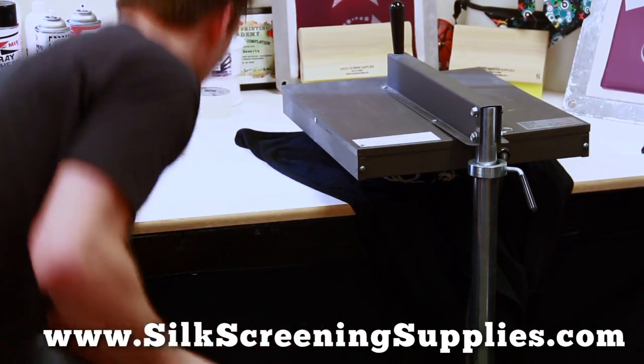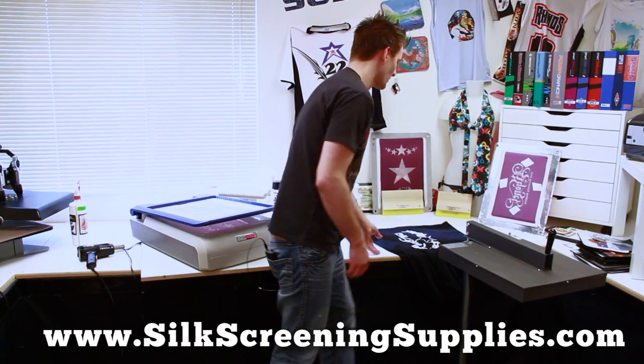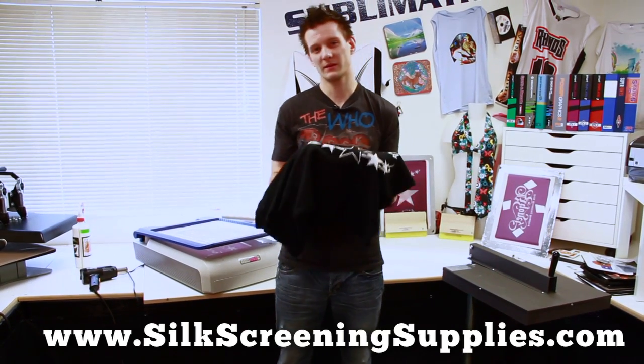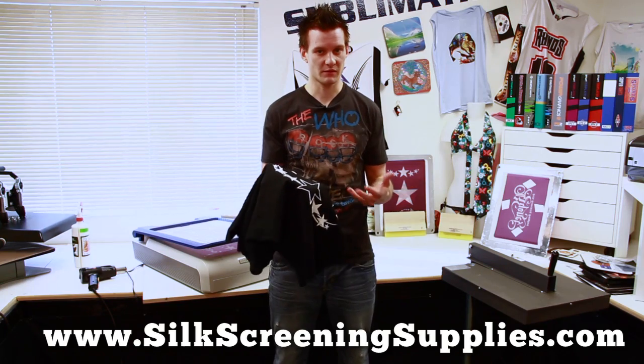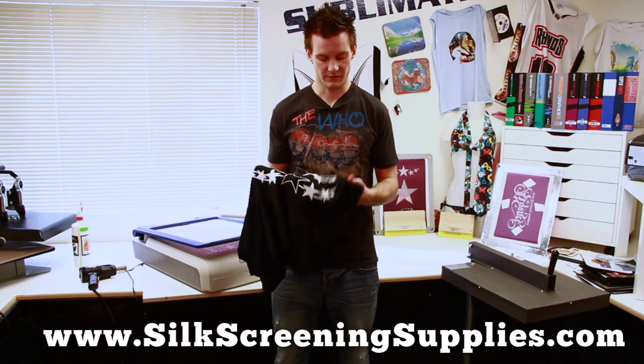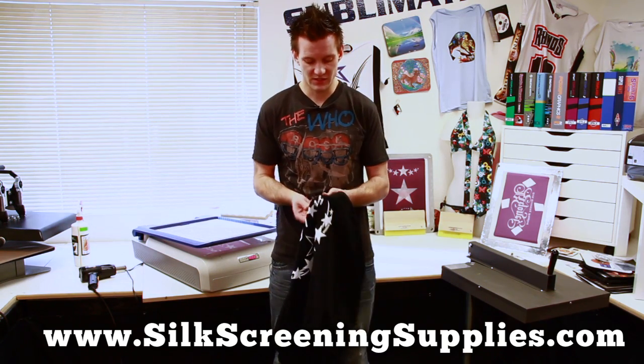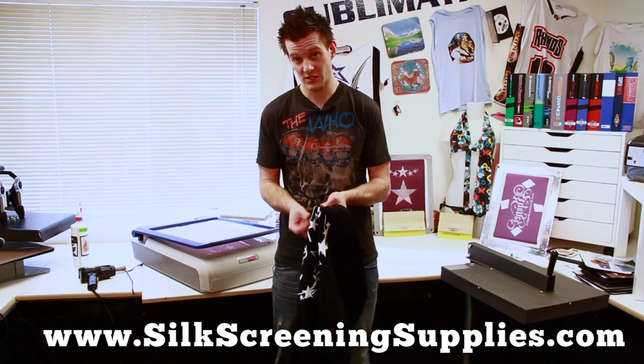There we have it — it's about 330 degrees now. You'll see it slightly melting. Plastisol has a distinct smell when it's cured — it's a little bit of a burnt smell, but you definitely want to use this in a ventilated room. This is completely cured now. We can tell that it's cured by slightly stretching the ink. You don't want to do this when it's super hot off the press, but we slightly stretch the ink — if it doesn't crack apart, especially with this thicker coat, we can tell that it's cured.